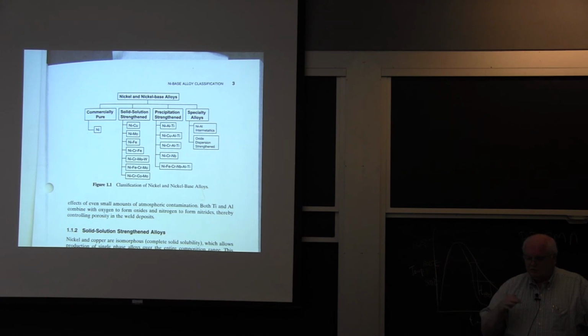And so I was teaching thermal at the time. I took my phase diagram books home, and I looked at it and I said, add, I don't remember, 0.2% nickel to your white gold, and then heat it up to this temperature to solutionize it, quench it, and then heat it up to this intermediate temperature, and see if you can get precipitation hardening. 450 Vickers.